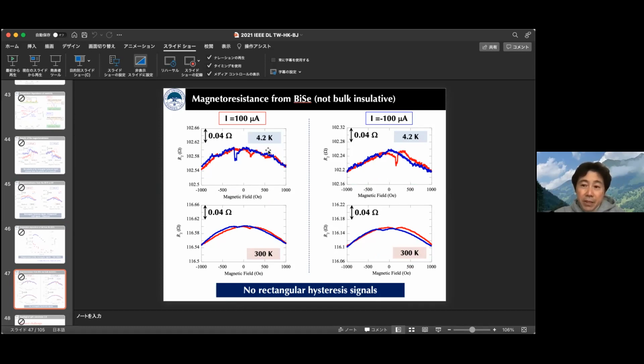This means the position of the Fermi level is very important because, of course, we partly access the topological state, but when the Fermi level is located in between the bulk bands, we can directly access the topological spin polarized state, and this allows the easy detection of the spin-dependent magnetoresistance effect. So that's a key to observe such kinds of effect. In this sense, material selection is very important. Thank you. Have I answered your question? Yes, it's very, very clear.